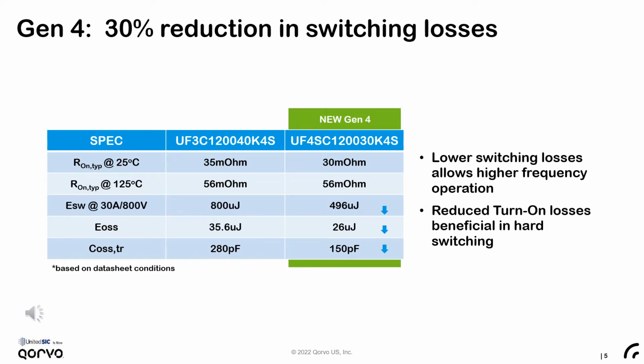The impact of this technology improvement is evident here, where we show our previous generation 1200 volt FET with our new 30 milliohm UF4SC120030K4S product. While the hot on resistance is comparable, the device offers a lower on resistance from room temperature up to 125 C. But despite the superior conduction losses, the Gen 4 device exhibits a lower switching loss, lower output capacitance, and lower EOSS. These performance advantages are beneficial to allow higher frequency operation and improve converter efficiency in both hard and soft switch circuits, as we'll see in later examples.